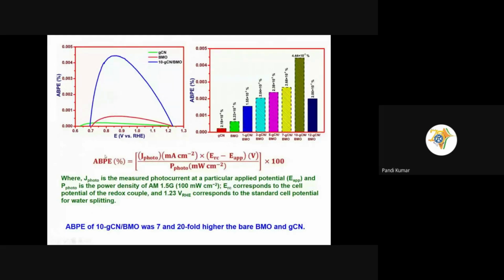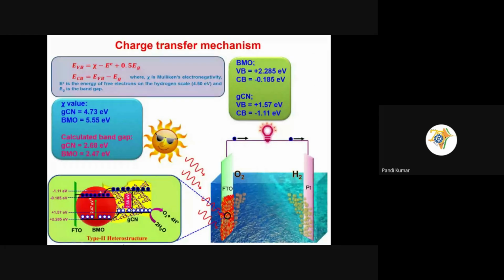Then we have calculated the efficiency for the different systems. It seems 10% shows 7-fold and 20-fold higher efficiency than the pristine material. Then we arrived at the type 2 mechanism based on calculation and values derived from the literature. The chi value we have taken from the literature for the material. Then we already calculated the band gap through the Tauc plot method. So we have substituted these values in the particular equation. Accordingly, we have derived the band positions of both materials. So finally, this position shows the type 2 mechanism for this one.